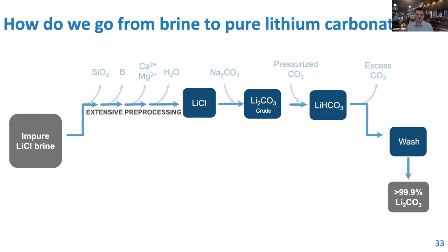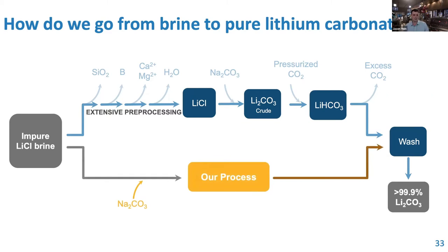So what this meant is that what would normally be the process where you take lithium chloride into lithium carbonate involves a multi-step process where you first do processing to get a much, much cleaner lithium chloride solution. There's then a lithium carbonation step, which is similar to what we do, this pressurized CO2 extraction via bicarbonate, and then onward. So this is a multi-step process, which is honestly very energy and material intensive. We simply drop that flow sheet, where our same impure lithium brine goes through simple carbonation and recrystallization, and we get the same level of purities as we get from these OEM-type vendors.